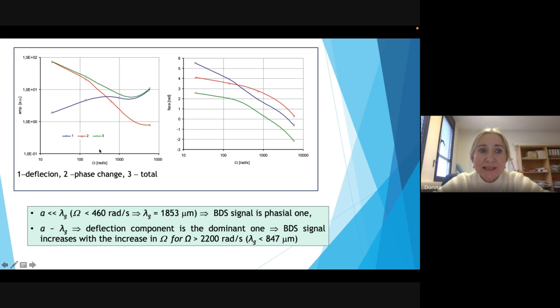Yeah. So what we see is that for relatively low modulation frequency, which means that the radius of the probe beam is much smaller than the length of the thermal wave in the medium in which the probe beam propagates, so if the radius of the probe beam is relatively small and the frequency is relatively low, the component that dominates in the total signal is the phase one. But if the radius of the probe beam is comparable with the length of thermal waves in the medium the beam propagates, the component that dominates in the total signal is the deflectional one. So just by setting properly the experimental conditions, we may arrange the experiment in such a way that we need to take in our analysis only one of the components of the signal.